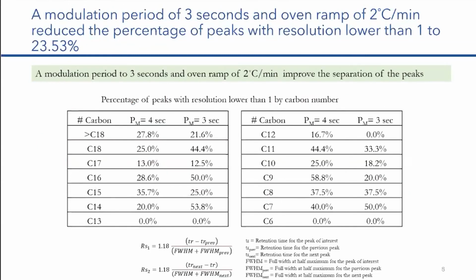So it has been found that a modulation period of 3 seconds and an oven ramp of 2°C/min reduce the percentage with resolution lower than 1. That means we are having a good resolution. Almost all the peaks in the chromatogram are separated, and we can proceed with the identification and the quantification.